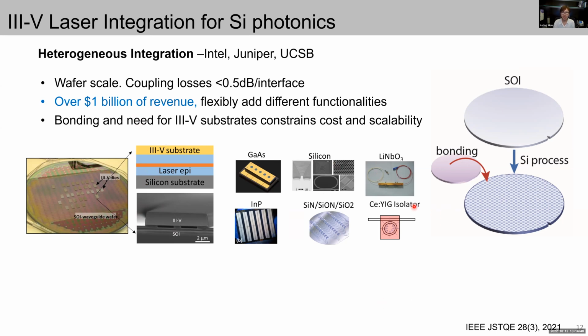In addition, this technique not only offers elegant paths for the inclusion of a laser source on a silicon photonics platform, but also makes it possible to flexibly add different functionalities, different materials onto the same chip, despite the material incompatibility. For example, indium phosphide materials for telecom communication, gallium arsenide-based material for 850 nanometer VCSEL, lithium niobate for modulators, InGaAs for photodetectors, silicon nitride and silicon oxynitride for ultra-low-loss waveguides, and YIG thin film for isolators.